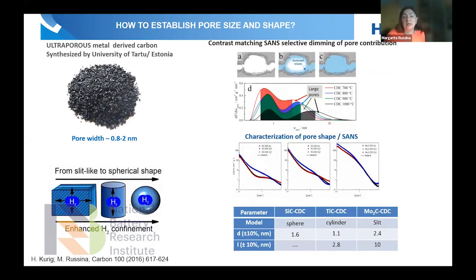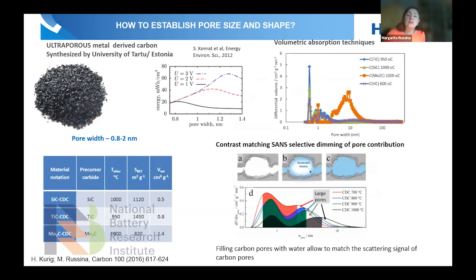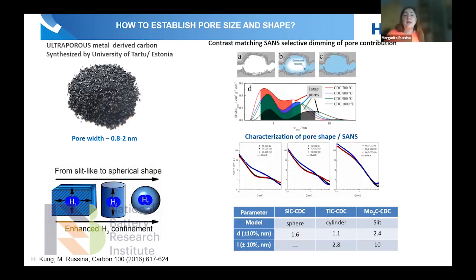And what we have done here is use the small angle technique, usually getting curves like that, which is the response to this density correlation. But what you can do in addition is to fill the pores gradually with some kind of material which has the same scattering length as carbon. In our case, it's water. So you put the water inside and gradually close down some of the pores. In this way, you can look at how the signal changes with the amount of water, and establish the size of the response much more precisely.